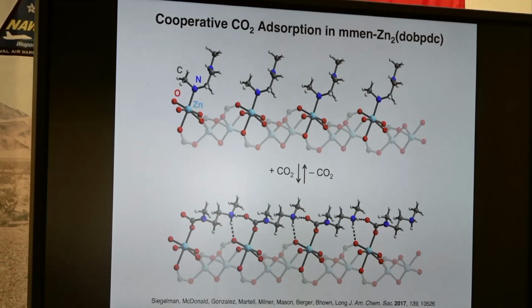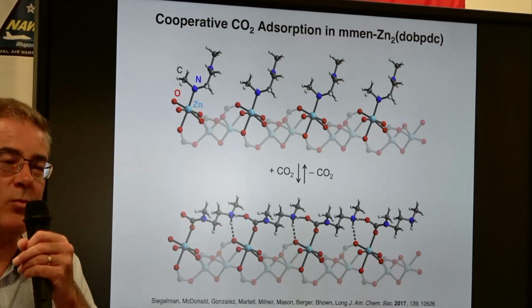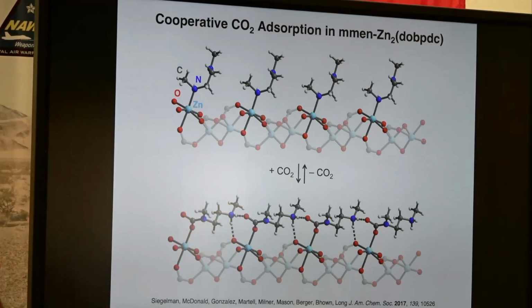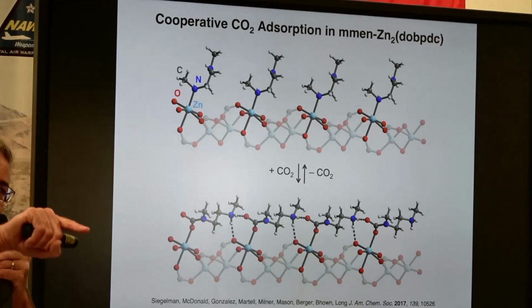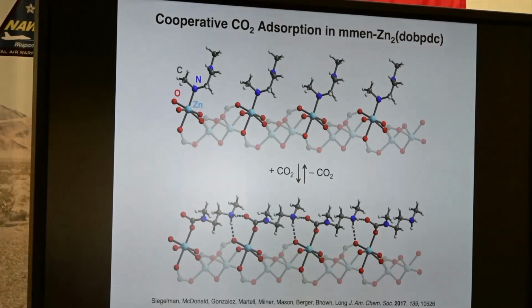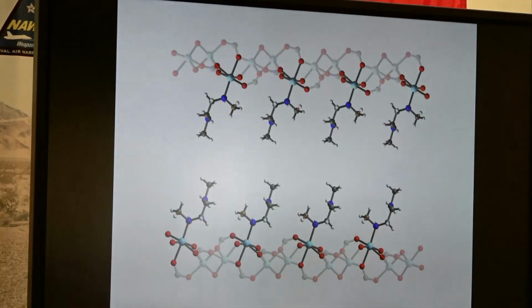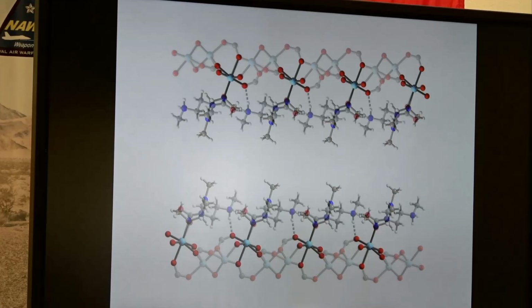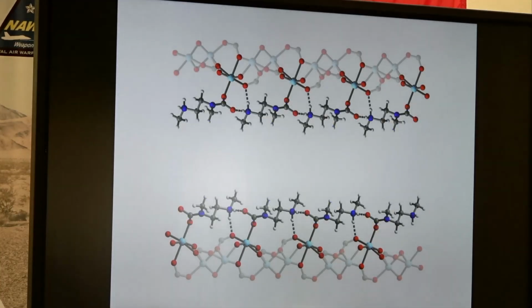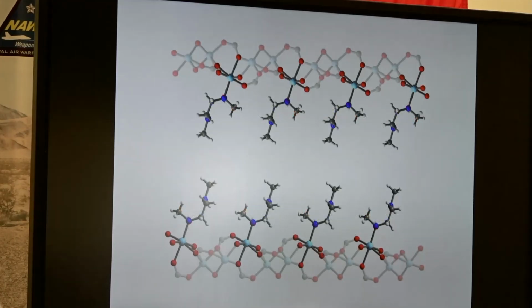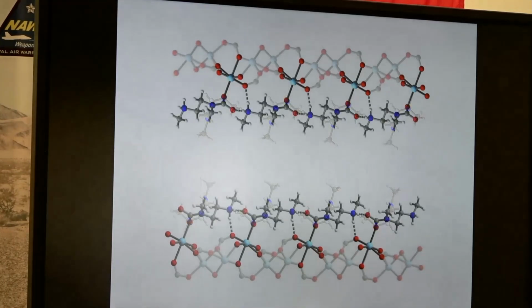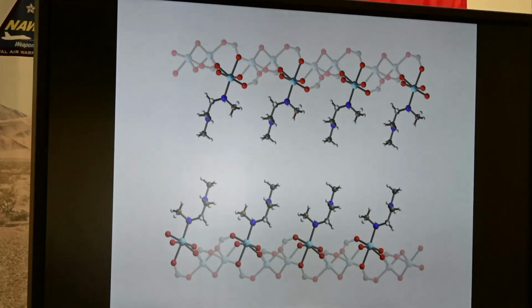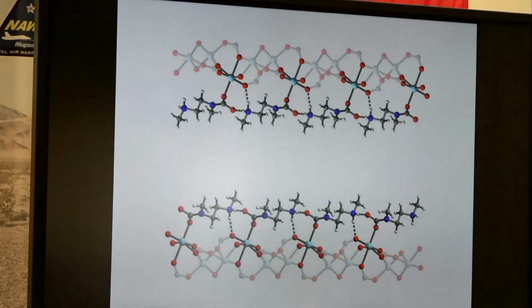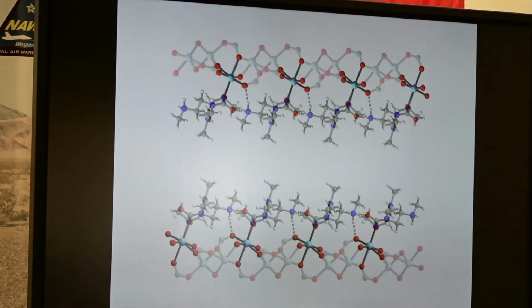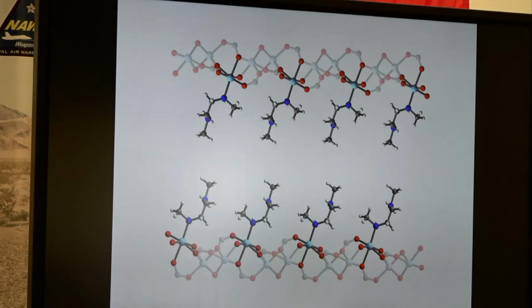So we got very lucky. The diamines are spaced just the right distance apart to form this one-dimensional ammonium carbamate chain. It means the first reaction site will actually lower the energy of the second and the third and the fourth and the fifth, and you get a chain reaction to form this polymer. And so very much like hemoglobin, this MOF will go and suddenly, at a very specific pressure and temperature, fill up with CO2, taking all those diamines to form ammonium carbamate chains. And so this is a breathing type of mechanism selected for CO2, very much like hemoglobin, but with a much higher degree of cooperativity. And you can see there's a gap down the middle of each channel for rapid incoming and outgoing gas transport.